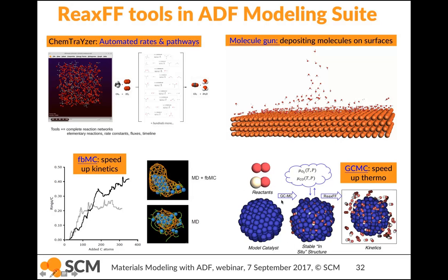And those will have different catalytic properties. So by doing first this grand canonical Monte Carlo, actually in combination with ReaxFF, and then having your stable nano catalyst under reaction conditions, then you can run reactive molecular dynamics and see, in this case, how that affects carbon monoxide oxidation to CO2. And then I mentioned already this Monte Carlo optimizer, so there's a tool available also for parameterizing or reparameterizing your own ReaxFF force field. And there's an advanced example on how to do that, actually make your first bromine force field.